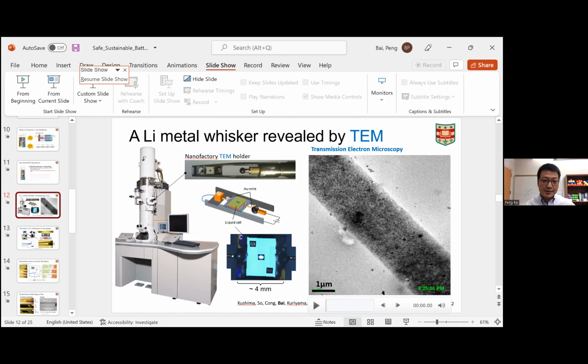And here, the whisker growth is still a mystery. We only have speculations, okay? The reason is that the electrolyte, the solvent we are using, is not ideally stable against the electrode. So it will have a reaction before the lithium plating. You will have a reaction between, for example, the copper foil and your electrolyte. The reaction product will create what you can call a passivation layer, but this passivation layer is not uniform. It has a patterned structure, and somewhere has easier access to lithium ions, somewhere is completely shut off. So when you have this non-uniform or highly localized access of lithium ions, of course, the growth will preferentially focus on that sweet spot.